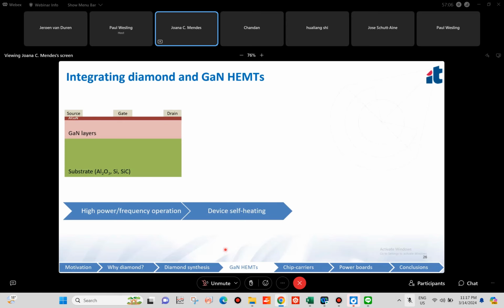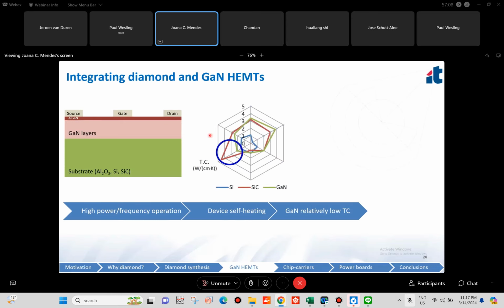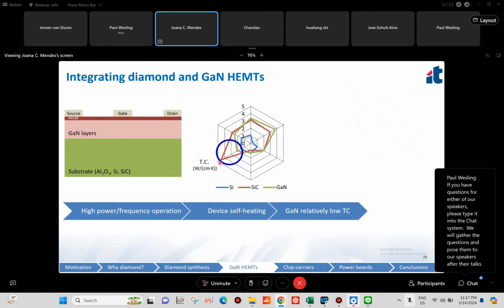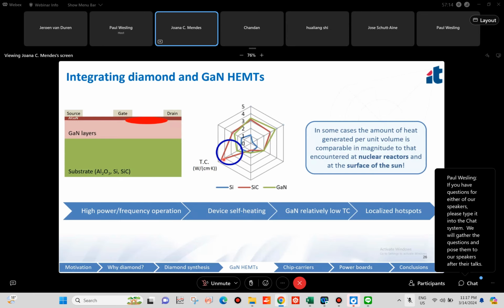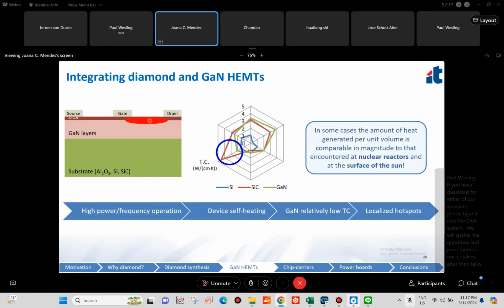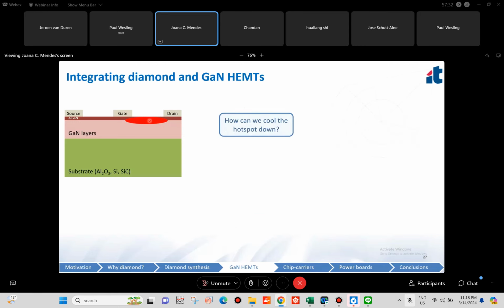However, we'll have device self-heating. And since gallium nitride has a relatively low thermal conductivity, at least compared with silicon carbide, we get the generation or the appearance of localized hotspots. And this is really serious because in some cases, the amount of heat generated is comparable to the one we find at nuclear reactions and nuclear reactors, and at the surface of the sun. So you really see that we have to cool these hotspots down. And how can we do it with diamond?